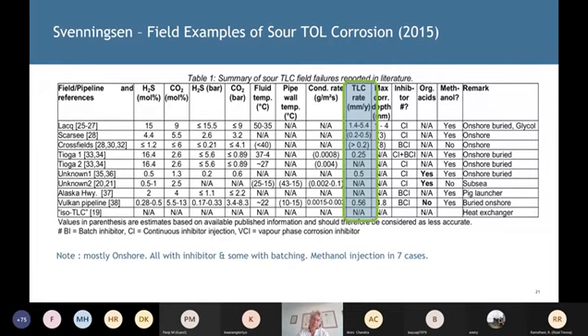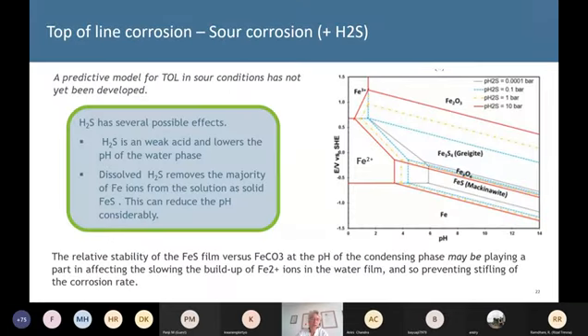Mike and I have currently been looking at a case with top of the line corrosion rates in a sour pipeline of about 0.7 millimeters a year. Very serious corrosion rates, very difficult to control, because also these don't arise at the start of the pipelines particularly. They can arise some distance along the pipeline. So it's rather different to sweet corrosion and very, very challenging indeed. So this is an area where there's further work needed. There's no predictive model for this at the moment.